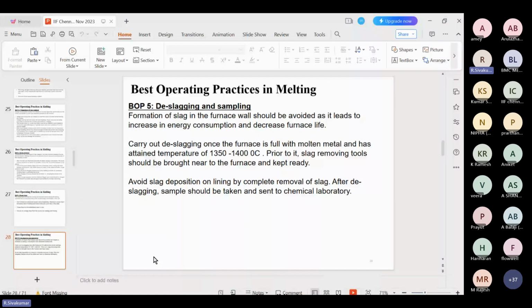After deslagging, samples should be taken and sent to the chemical laboratory. For sampling, the industry's practice is mostly spectro testing, and the result arrival takes around 7 to 10 minutes. This has to be minimized. So the spectro lab should be very close to the induction furnace area, so that once the sample goes to the tester, the result is given to the melt supervisor within 2 to 3 minutes. As much as possible it is reduced, your melt timing is also reduced, your energy consumption is also reduced.